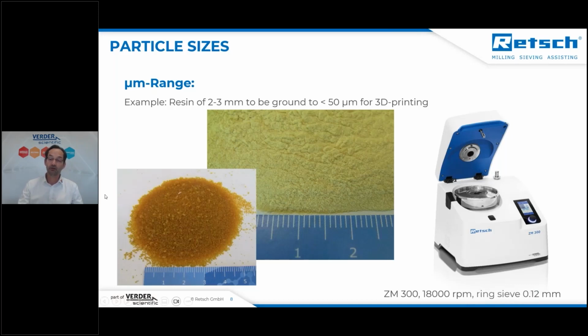And here we have used an ultracentrifugal mill, ZM300, with a revolution speed of 18,000 RPM. So this is a very high speed. I will tell you later on what this means. And using a ring sieve of 0.12 millimeters allows us to grind more than 60–70% of the material to less than 50 micrometers. So what happens inside the ultracentrifugal mill?